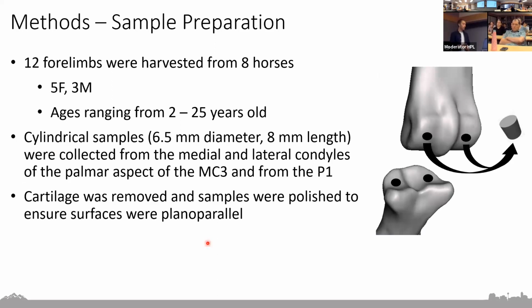So into our sample preparation, we collected 12 forelimbs from 8 horses that were euthanized for reasons unrelated to this research. We had 5 females and 3 males with ages ranging from 2 all the way up to 25 years old. And then we cored out some cylindrical bone samples, much like the one you see on the right-hand side here.